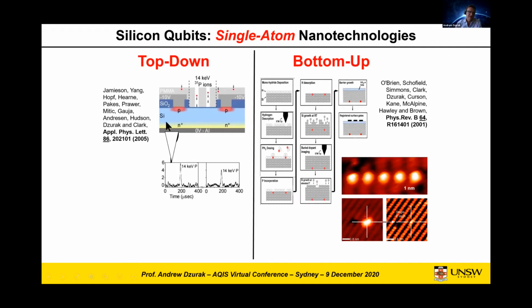fabricating particle detectors, ion impact detectors, in situ into the chip. And this was demonstrated in this paper in 2005 in APL, where it was shown that low energy 14 kilo-electron volt phosphorus ions, when they impinge into the chip, could be detected in this PIN detector structure, and one could register these impacts with high fidelity. This work's since been continued by David Jamieson in collaboration with Andrea Morello's group, and they've recently shown some really outstanding new results in the ability to count these atoms into the device.